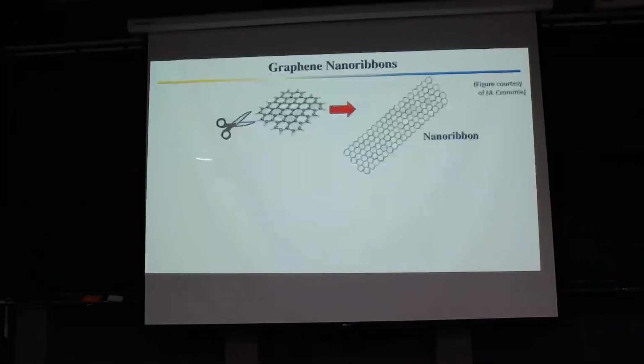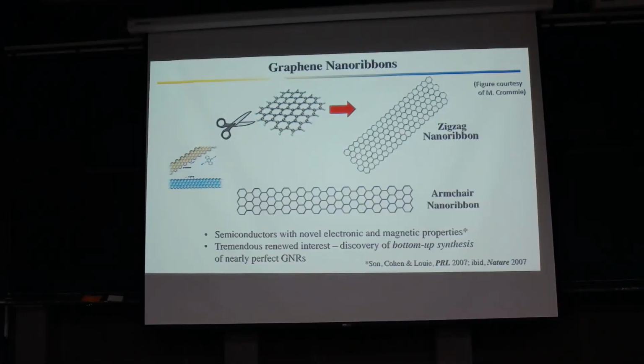And so you take graphene and then you cut out a small ribbon with a width of 1 or 2 or 3 nanometers, but very long along the length direction. Then this is what we call a graphene nanoribbon. Of course, you could cut it in different ways. You could have a ribbon with different width and different edge shape. This is what we call a zigzag graphene nanoribbon because the edge looks like zigzag. And then this is what we call armchair graphene nanoribbon.